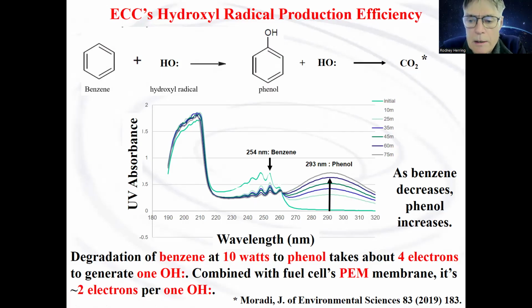And we find that going through the reactor, 4 electrons will generate 1 hydroxyl radical. But if we do combine this with the PEM membrane of a fuel cell, we can increase this efficiency to 2 electrons passing through the reactor for 1 hydroxyl radical. So it's really quite amazing at how strong it is.